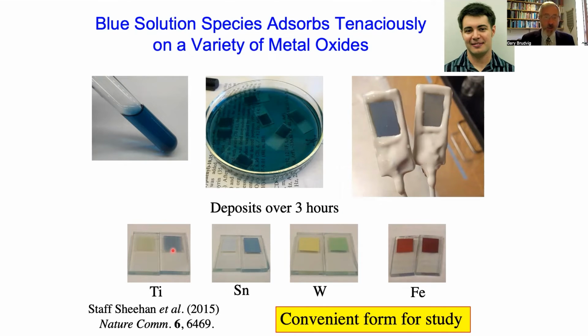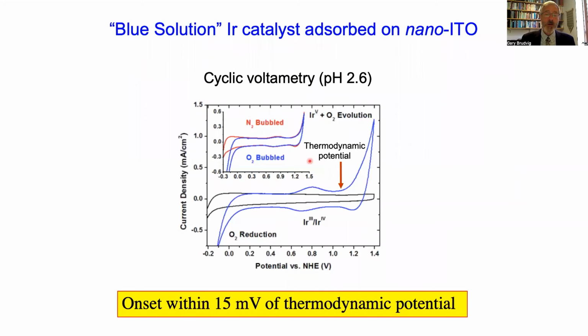Of course, this now allows us to carry out electrochemistry by using a conducting oxide electrode, nano-ITO, to carry out cyclic voltammetry. And this blue trace shows the cyclic voltammogram of the adsorbed catalyst on the surface. And what we see is a reversible iridium 3,4 couple, followed by a catalytic wave with an onset that is essentially right at the thermodynamic potential. So it's a very low overpotential for this catalyst.